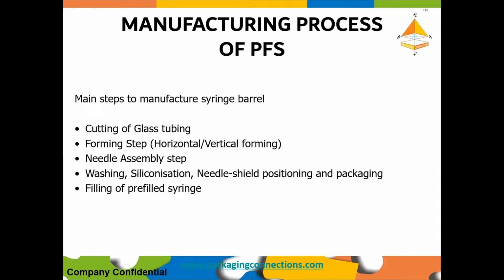Manufacturing of PFS, when we talk about glass, basically starts with the cutting of the glass tubing, then forming, and then needle assembly, in case it is a staked needle. If it is not a staked needle, then it's not required. Then it will move to washing, siliconization, and again, if it was a staked needle, the needle shield will be applied. If it was not a staked needle, then the Luer lock cap will be applied, and then these will move to the filling line. So filling of the prefilled syringe is basically at the pharma company.